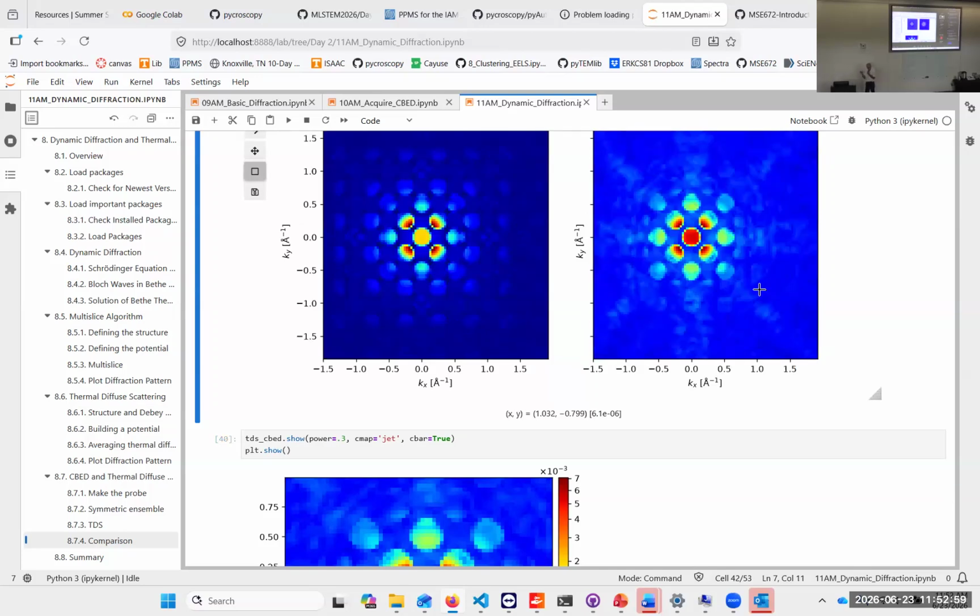And the larger your cell is, the higher is the position in the diffraction pattern, and the smaller the pixel size in real space is. So that is how far out you go in reciprocal space. The pixel size in real space is the field of view in reciprocal space, and vice versa, the pixel size in reciprocal space is the field of view of, and so that is directly related to the resolution you get.